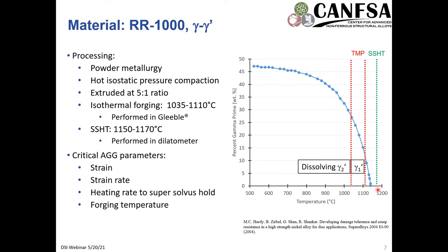And through my experiments, as well as exploring literature, some of the critical abnormal grain growth parameters that we've seen have been strain and strain rate during the deformation, as well as heating rate to the super solvus heat treatment, as well as the forging temperature during isothermal forging.